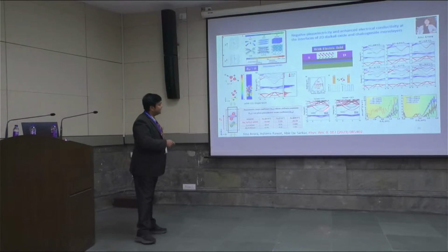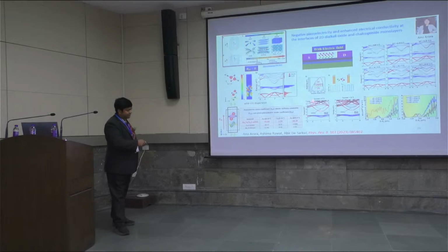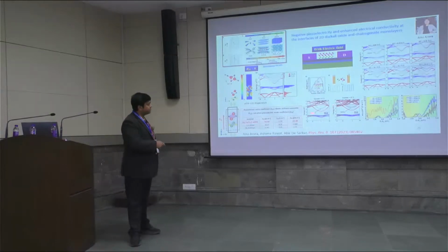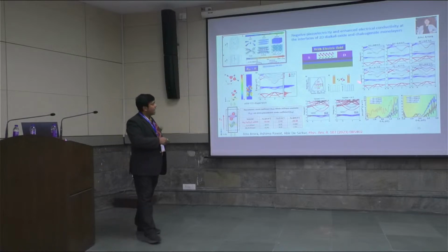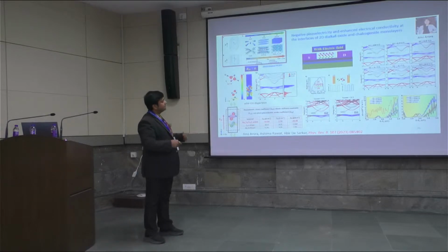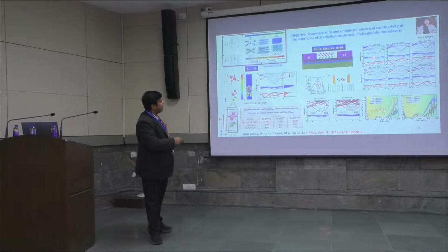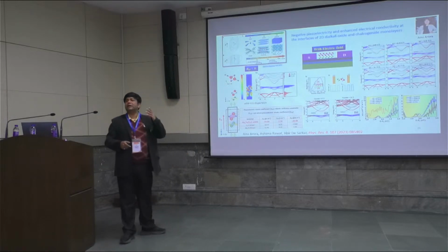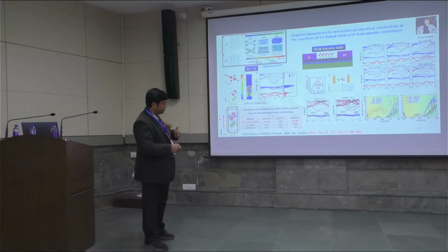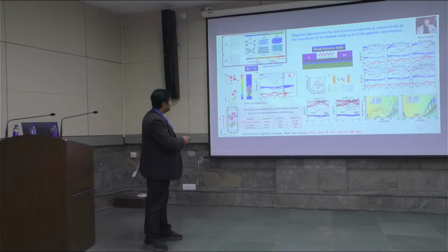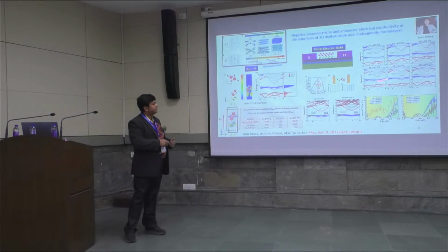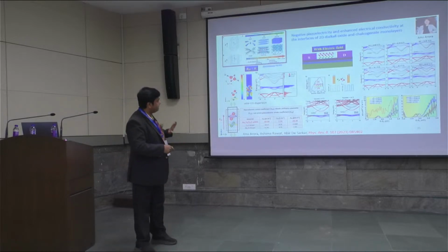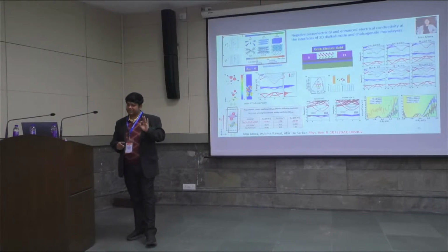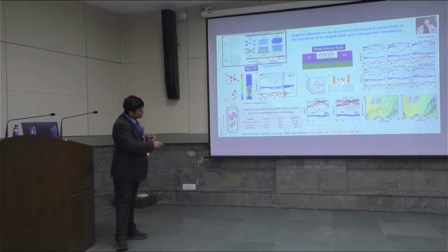And these monolayers show nearly free electron gas states having a parabolic dispersion similar to that of graphene. This arises from the image potential surface states as in graphene. In this van der Waals heterobilayer, when the electric field is applied along the plus Z or minus Z direction, these NFE states reach the Fermi level and enhance the electrical conductivity. When a positive electric field is applied along the plus Z direction, the red bands of Na2Te move upward relative to the blue bands of Cs2S, and when a negative electric field is applied, the band movement is opposite. And now the closing and opening of the band gap in the presence and absence of electric field can be utilized in digital electronics.